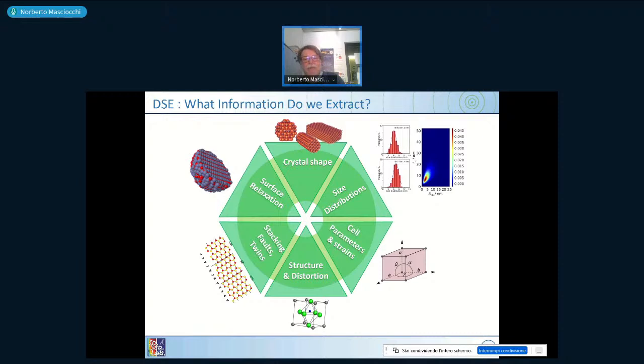It means having the full plot of a crystal size in a two-dimensional space. You can get cell parameters and strains or modification of the cell parameter, for example, by changing the size of the material. You may have structure and distortion. You will see some example later. You can study the presence of other kinds of defectiveness, which is stacking faults, twinning, and so on. And you may have surface relaxation. That means that the surface atoms are farther away from the next neighbors than the center one. So you have a cell which is changing radially with your system. At the center, the system is much more dense than in the periphery.